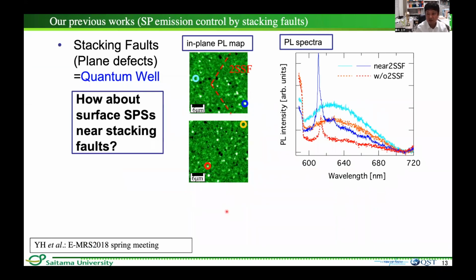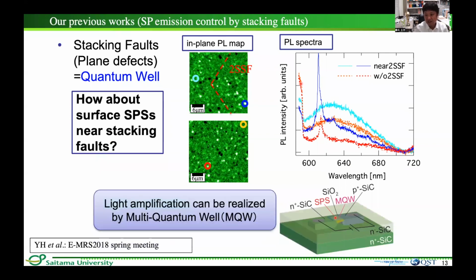Next, I will talk about the single photon control by stacking fault. SiC is a very unique material. Stacking fault, in another word, plane defect, is equivalent to a quantum well. So we investigated whether there is a difference between SPS near stacking fault and far from stacking fault. As a result, SPS near stacking fault has a much higher single photon emission rate. Therefore, light amplification can be expected using a multi-quantum well formed by a stacking fault array.